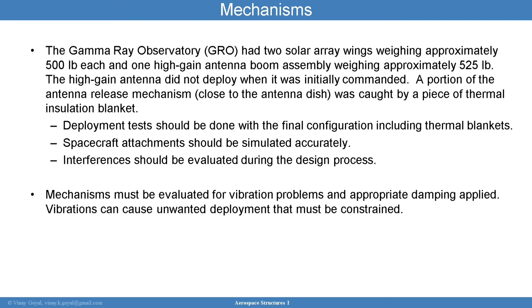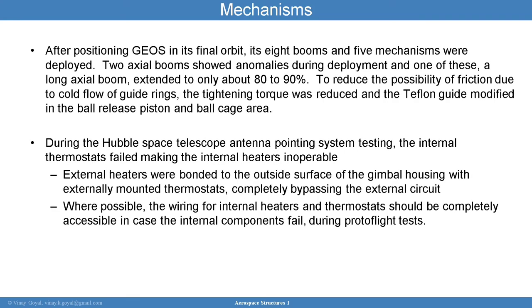Mechanisms should be evaluated for vibration problems, and appropriate damping should be applied. Vibrations can cause unwanted deployment that must be constrained. After positioning the GRO in its final orbit, there were 8 booms and 5 mechanisms that were deployed. 2 of them showed anomalies during deployment, and one of these long axial booms extended only partially. So to reduce the possibility of friction due to cold flow of guide rings, the tightening torque was reduced and the Teflon guide modified in the ball release piston and ball cage area.